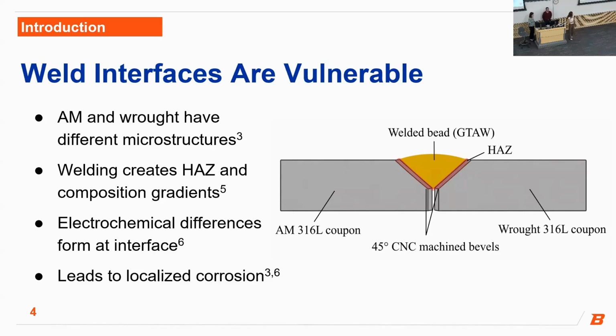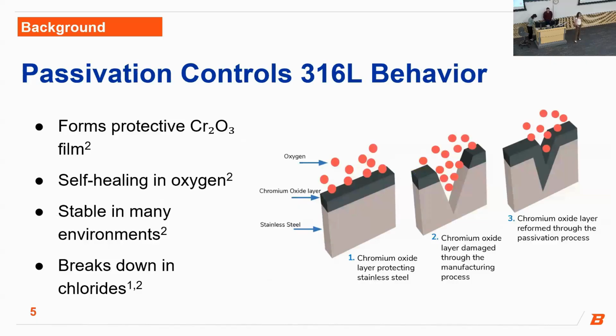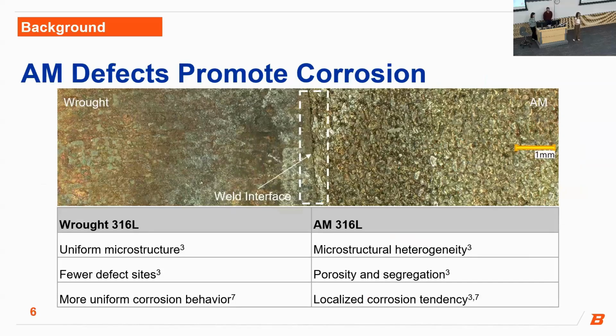With this problem, first we looked at why stainless steel can typically resist corrosion. 316L stainless steel forms a protective chromium oxide passive film, and it's able to self-heal in the presence of oxygen. This film is stable in many environments, but in chloride environments, it can tend to break down, and this breakdown becomes more likely when there are differences within the microstructure. Here we have one of our welded samples. On the left, we have our wrought. On the right, we have the additively manufactured, and highlighted in the dotted box in the middle is the weld interface. The wrought material has a much more uniform microstructure, while the additively manufactured material has more defects like porosity and segregation. These defects can act as initiation sites for localized corrosion.